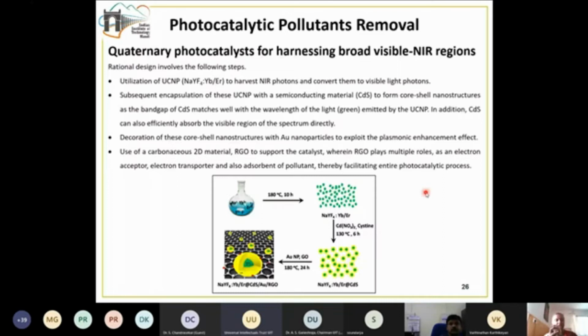Then we took the upconversion nanoparticle having ytterbium and erbium, which will be emitting green light. Then we coated this material with another material which has the capability to absorb the green light emission. So we coated it with a semiconducting material, cadmium sulfide. Cadmium sulfide has a band gap of 2.4 electron volts, which converts into about 540 nanometer, which is in the green light region. So this green light, which is emitted from the upconversion nanomaterial, gets absorbed by the cadmium sulfide.